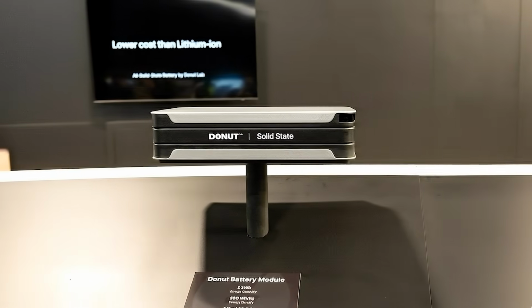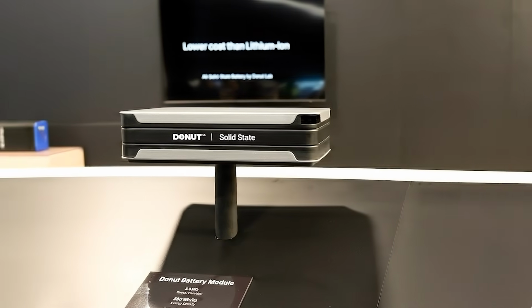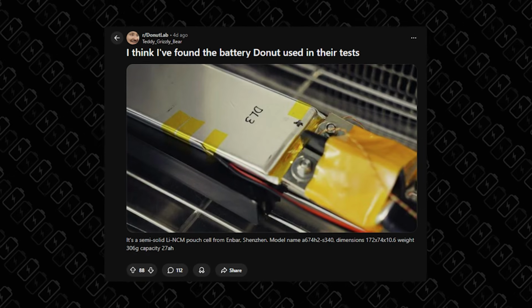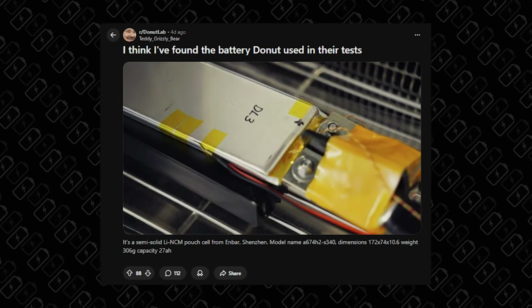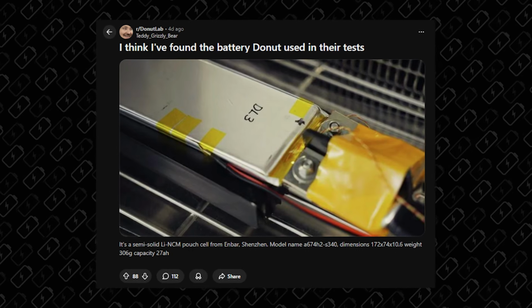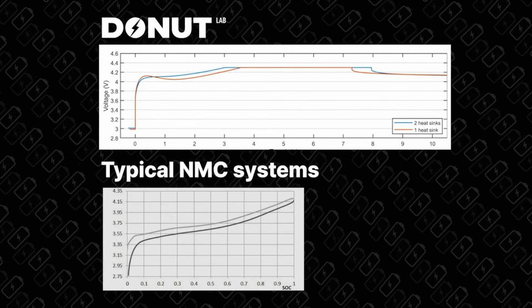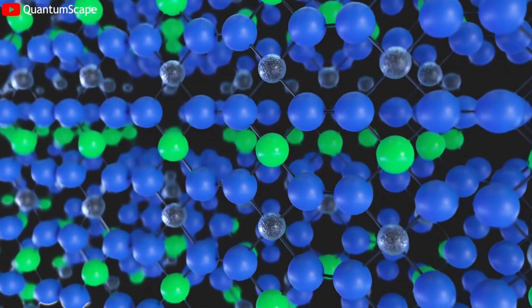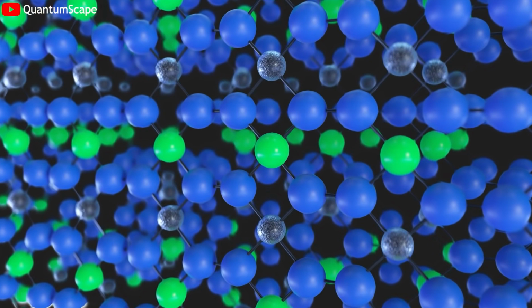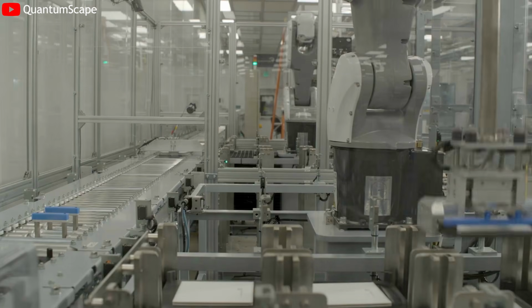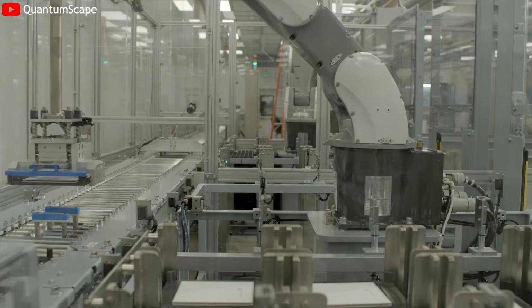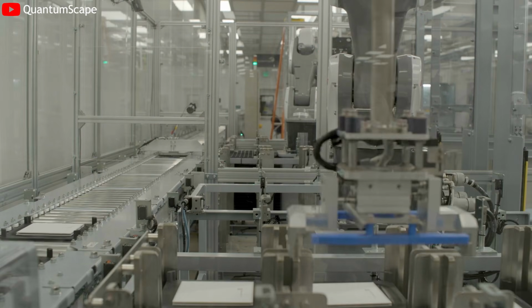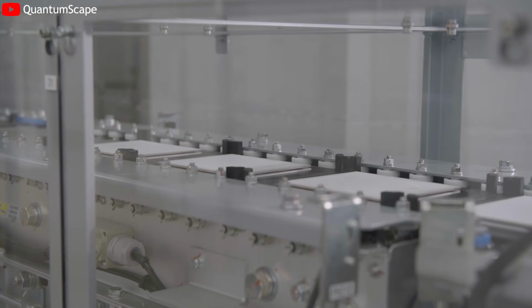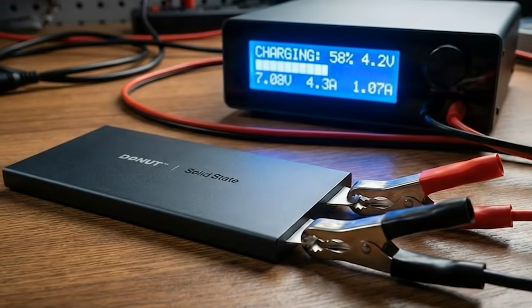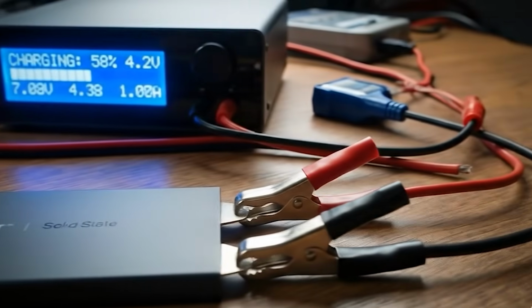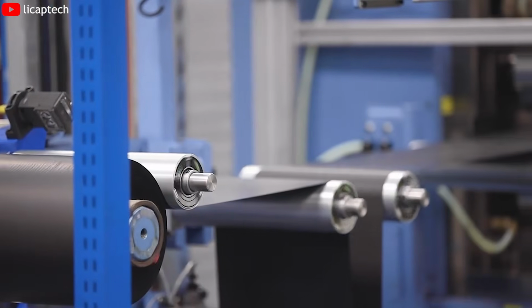So, is this technology a breakthrough or a branding exercise? The origin of the cells, potentially sourced from Enbar in Shenzhen, aligns with semi-solid lithium NCM technology. The voltage curves resemble lithium-ion behavior. The thermal claims exceed typical lithium-ion thresholds without detailed supporting chemistry. The absence of long-term cycle data contradicts what we know about durability challenges in solid-state research. The energy density does not clearly surpass established NMC cells, and the observed swelling hints at liquid components within the system. Does that mean the technology lacks value?